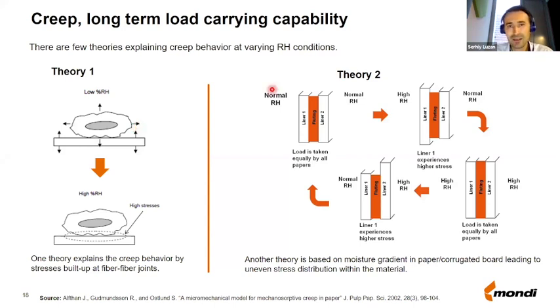And the second theory looks at creep on the level of boxes. Let's imagine you have a liner 1, fluting, liner 2. At first you have a normal humidity outside the box and inside the box. And then once the humidity outside the box is increasing, liner 1 starts to absorb the humidity first. It starts to expand. And the fluting and liner 2 have not expanded yet. As liner 1 expands more, it is taking all the load, and therefore it is damaged more.